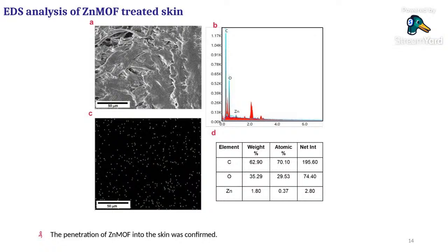Then we looked at whether the unhairing process is taking place. We rubbed the surface so that the hair will come out. Once it is done, it is completely washed, and we looked at it under the scanning electron microscope. We wanted to see whether the zinc MOF goes inside the follicles in the hair. What we are seeing, all the dots, is actually zinc MOF getting penetrated into the skin. That is happy news for us, because when the zinc MOF goes into the skin, it is an activity process to remove the hair from the skin.